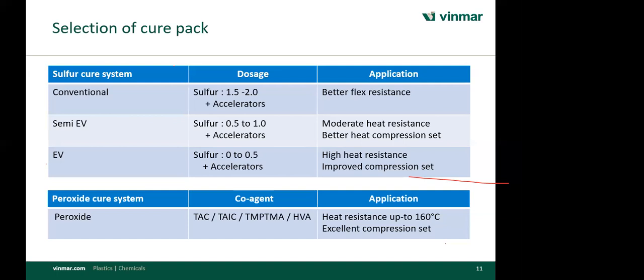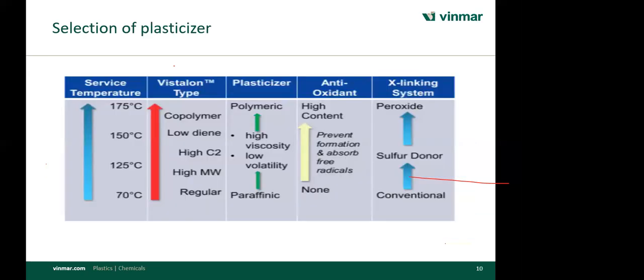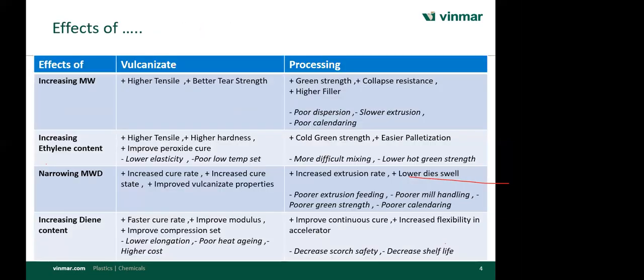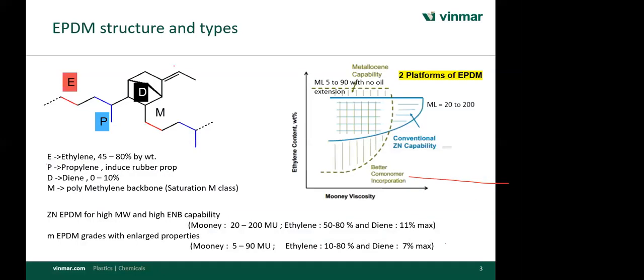Okay. And how can we improve green tack in EPDM compound? Let me go to my slide. Are you talking about green strength, or green tack? Green tack. See, if you want more tacky EPDM, you have to go for more propylene content EPDM. You have to change your polymer. Select the correct polymer. Propylene induces the rubber property, and rubber is tacky. If you take natural rubber, you find it tacky. The other component is ethylene, which does not give you the tack, it gives the strength only. So you select the polymer where the propylene content is higher.